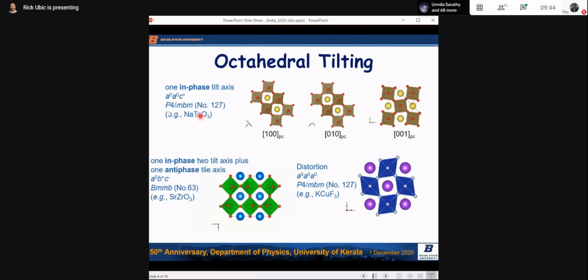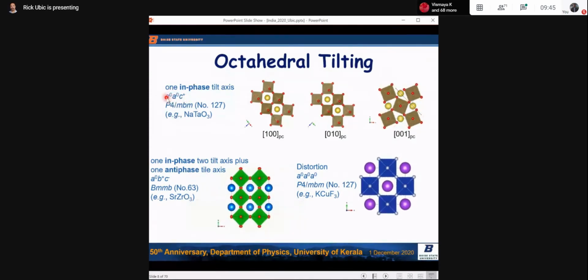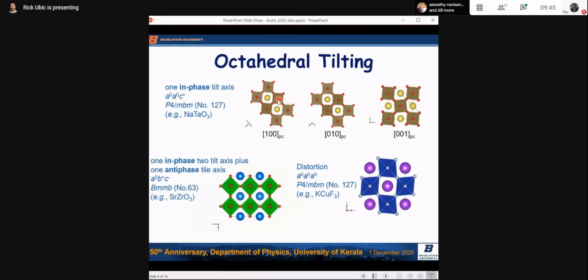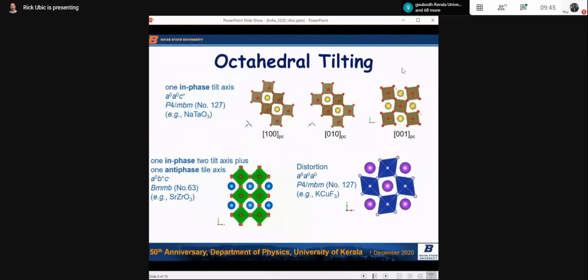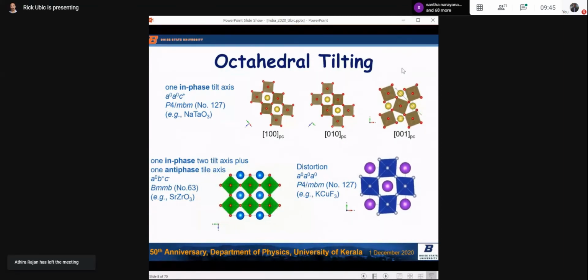This here is an example of one in-phase tilt axis. There's a shorthand for these tilts. You don't really need to know this, but the 0 up here means untilted. So it's untilted about this axis, and it's in-phase tilted about the c-axis. If we look down the A or the B, we essentially see nothing. You can see one of the oxygen vertices moving a little bit, but there's no tilting of the octahedra. Whereas along C, you can see that there is tilting. It's in phase because, remember, these octahedra are stacked along the C direction, and I only see one octahedron. So the ones below are tilting exactly the same as the ones above. They're in phase.